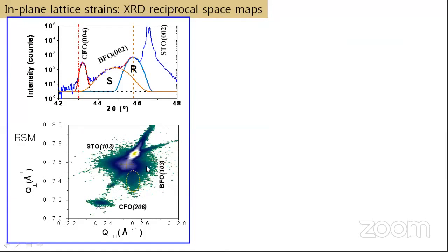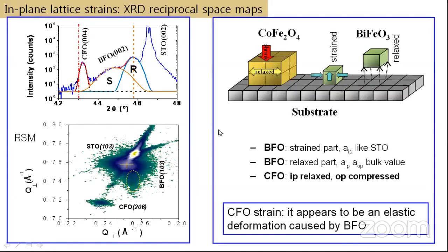We measured the in-plane lattice parameter, but unexpectedly, for cobalt ferrite, it shows the in-plane is relaxed and out-of-plane is compressed. Also for bismuth ferrite, as I showed, there are two cases: in one case the bismuth ferrite is strained, and in another case it is relaxed. This unexpected thing, where cobalt ferrite is relaxed in plane and compressed out of plane, is due to the elastic coupling between your bismuth ferrite and cobalt ferrite here.